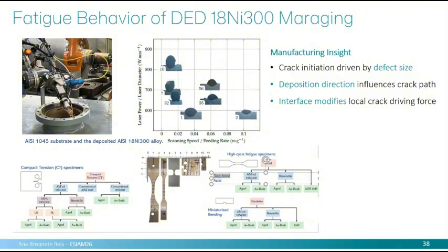Again, we knew that the part that we need to understand is the manufacturing, because cracks will be initiating by the defects that come from all the process. Also, the deposition strategy will influence the defects, and also the interface, as we see. And this afternoon, you can see a lot of details of this work from Jill.